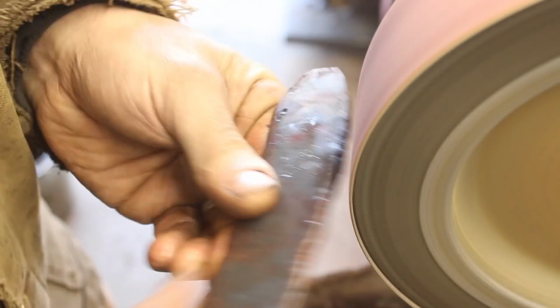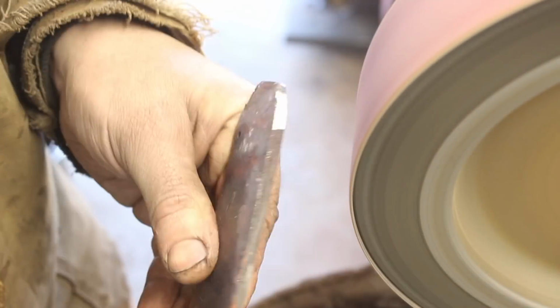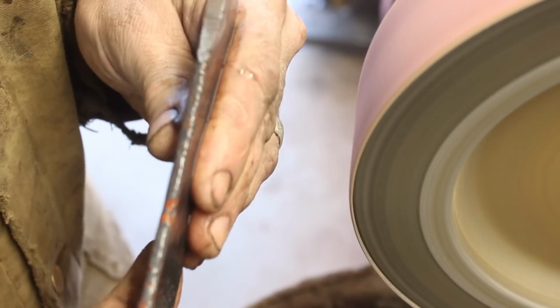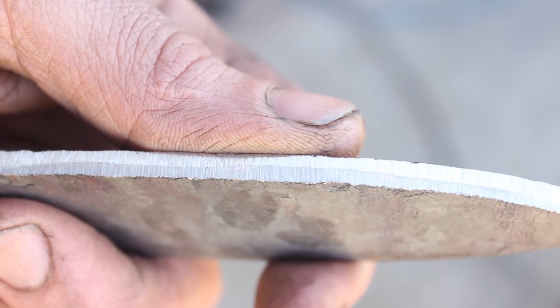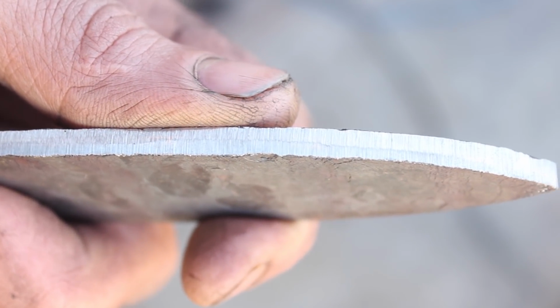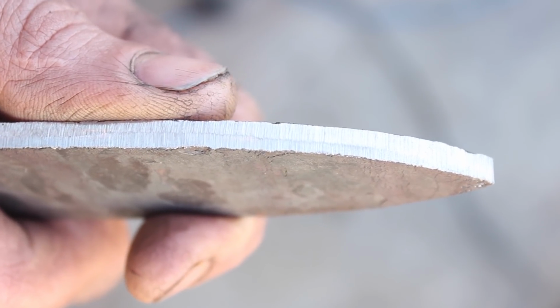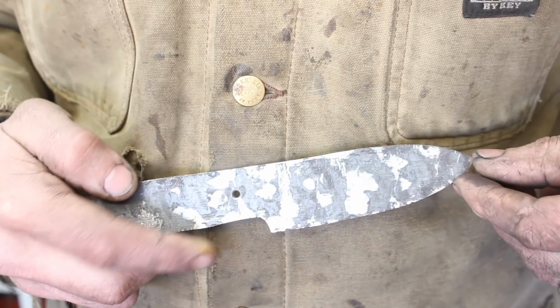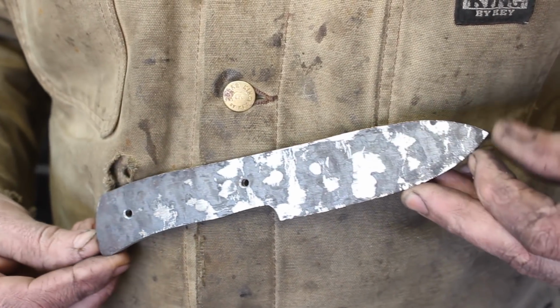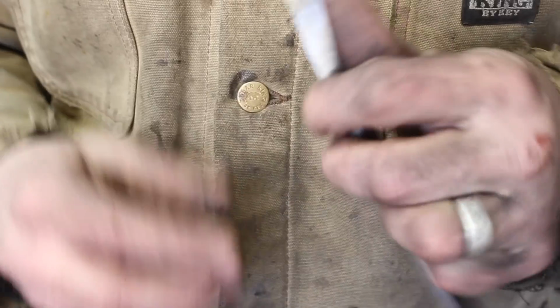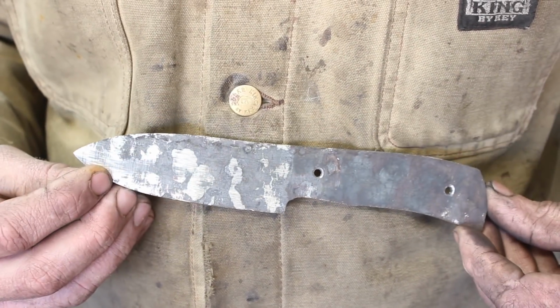So I'm going to go ahead and grind off the edges and inspect it and see what we have, if this is a solid billet or not. And it appears that it is. It also appears that the spots in which the copper was squeezed out, the steel seemed to forge weld together solidly. So that's interesting as well.